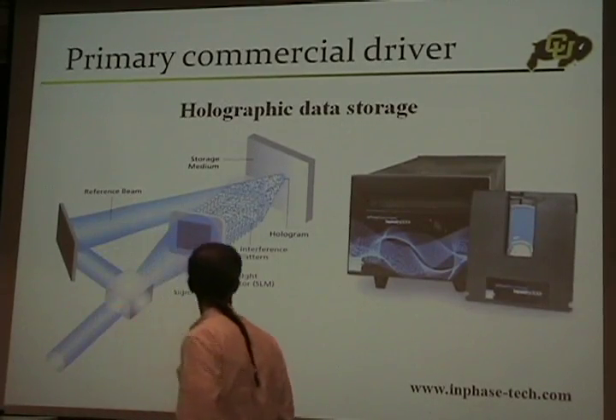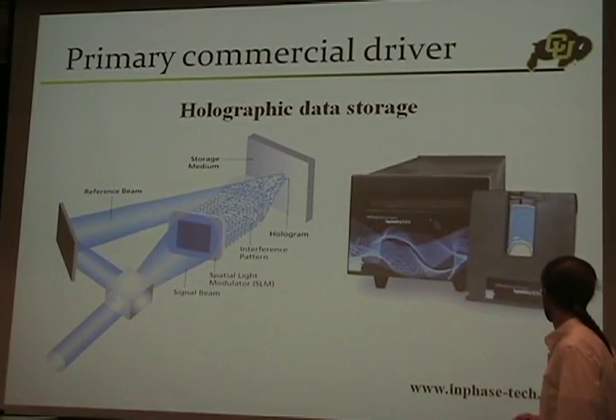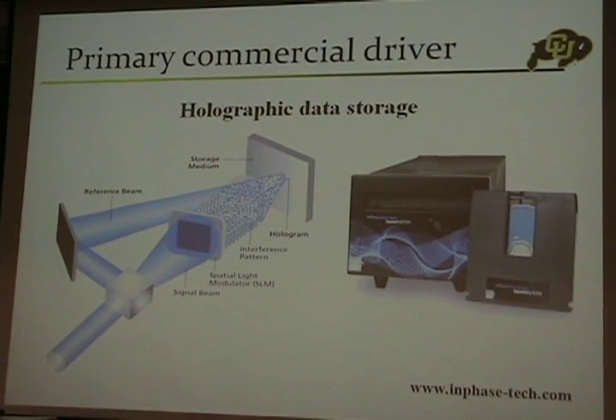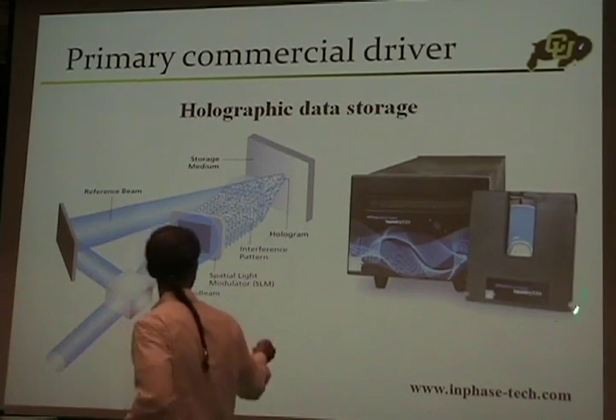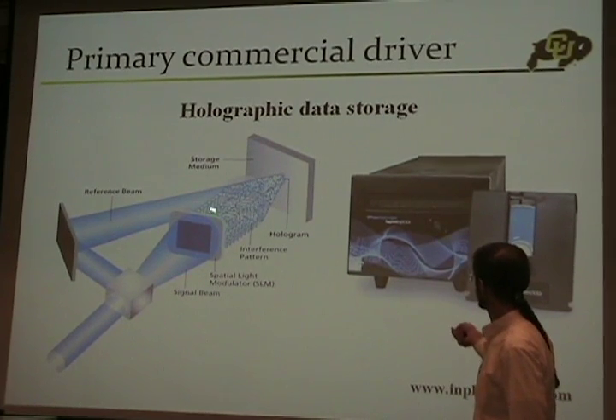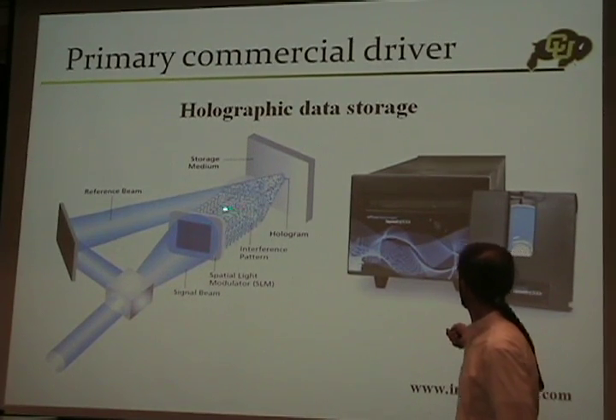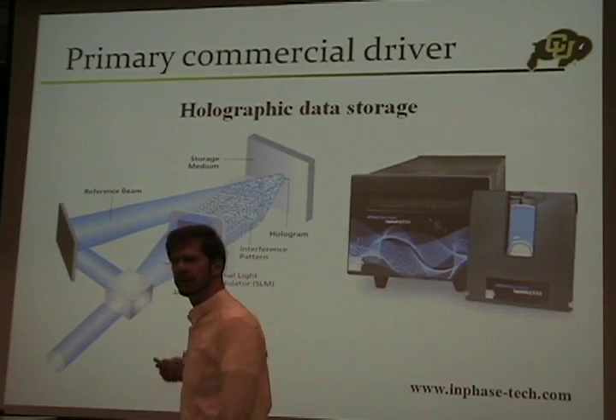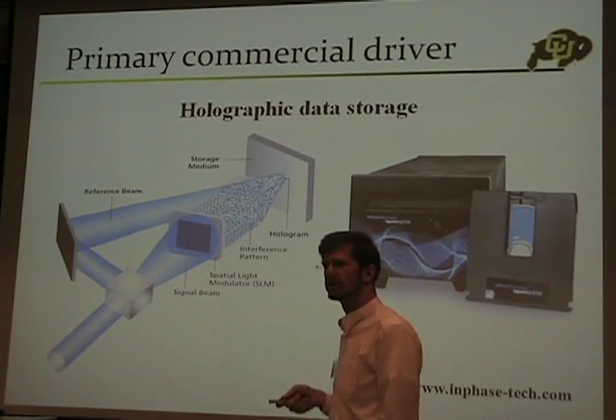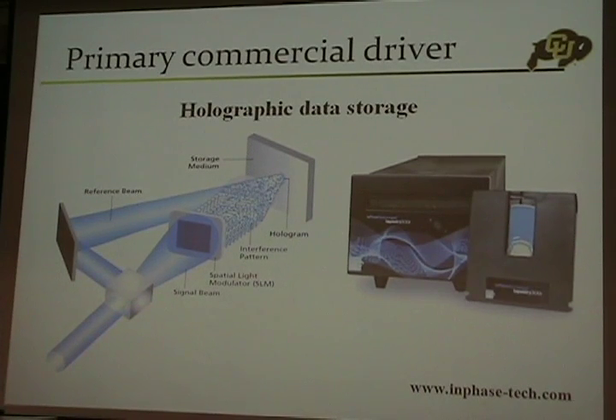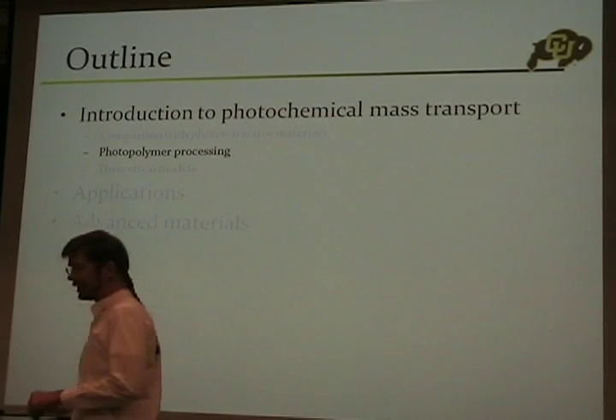The driver for photopolymer development has been this group over at InPhase, spun off of Bell Labs. They're releasing products — this is one of their disks, which I've taken apart to get some of the material to show you. These are 300 gigabytes on a single disk. It's holographic storage where you split the beam, go through a megapixel SLM, record one million bits of data at a time. Because it's a thick material, you can overlap hundreds or thousands of holograms at one location through angle multiplexing and store lots of data.